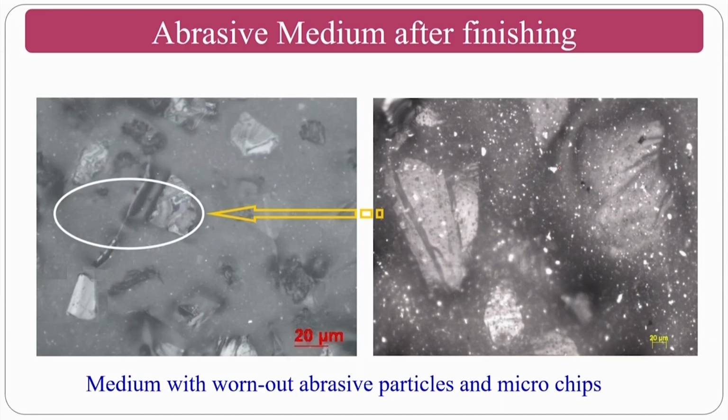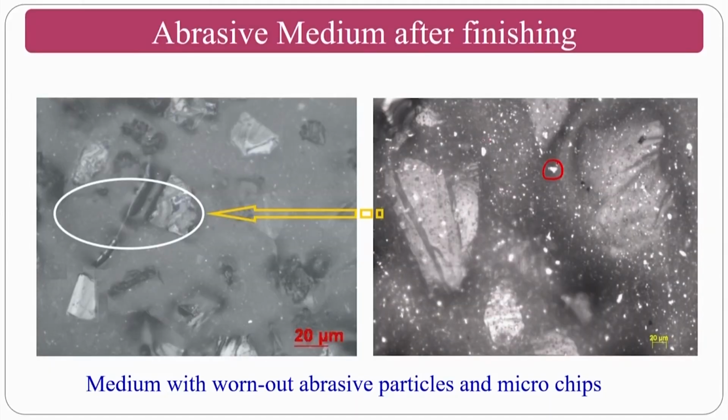Once the medium's weight gains 10% of its own weight, that means 1 kg, that means 1000 grams, if you measure your weight after a few experiments and it is 1100 grams, then you have to discard the medium.